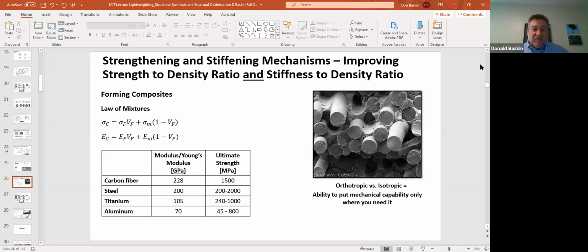One thing I haven't talked much about so far is improving the stiffness to density ratio, because a lot of structures are not strength limited, but rather stiffness limited. So creating a composite is one of the few ways you can engineer a material to be stiffer than it would be from the base material. Most steels, stainless steels, high alloy steels, low alloy steels, carbon steels, pearlitic steels, all have very close to the same Young's modulus. It changes very little, only a couple of percent. So you can't really increase the stiffness to density ratio by the strategies I showed you before, by alloying either aluminum or steel. But by forming a composite, you can very readily improve the stiffness.